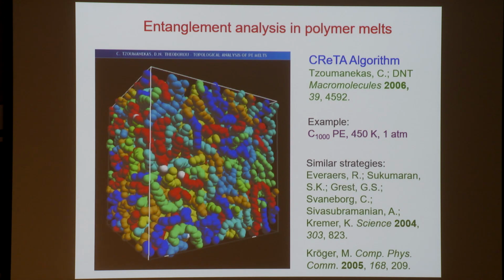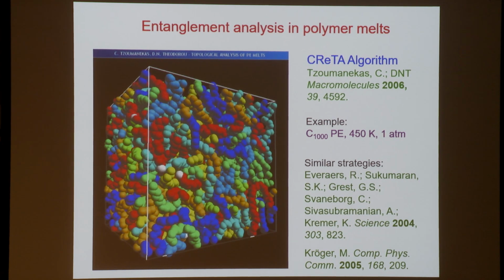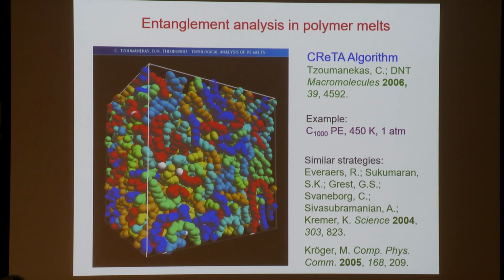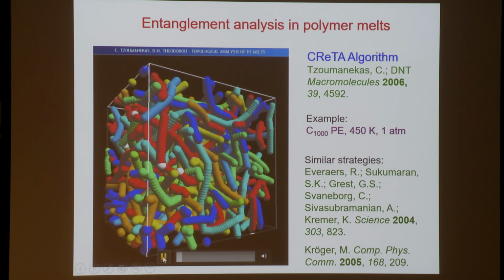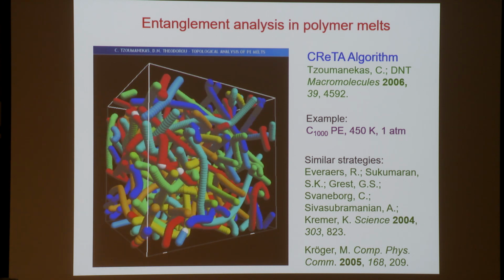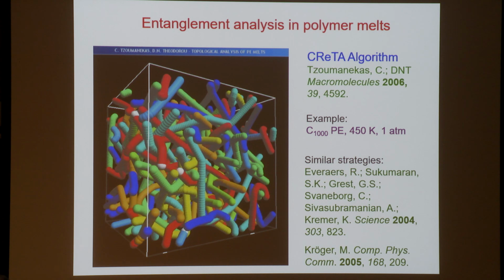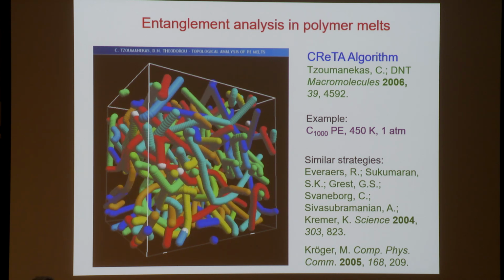The fact that we can equilibrate very long chain polymers gives us access to entanglements. So we can start from a well-equilibrated atomistic polymer configuration, such as this one. This is polyethylene. And then we can subject it to topological analysis to identify entanglements in three-dimensional space. Our group and other groups have developed algorithms for such topological analysis. I show you here the results from CReTA, contour reduction topological analysis. This fixes all the chain ends in the system and proceeds to reduce the diameters of the chains and the contour lengths of the chains in such a way that two chains cannot cross each other.